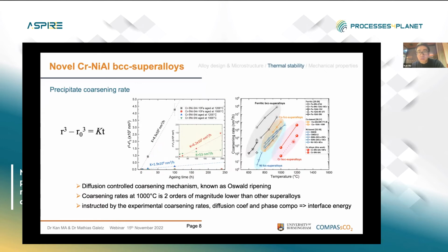And also, if we compare with the other common superalloys, cobalt and nickel FCC superalloys, the coarsening rate of the precipitates in chromium is much lower than in the other superalloys, which demonstrates quite good thermal stability of this material at high temperature. And with this experimental result, we can also deduce the interface energy. There is some experimental work and some simulation work ongoing with our partner VTT to validate this interface energy measurement as well.